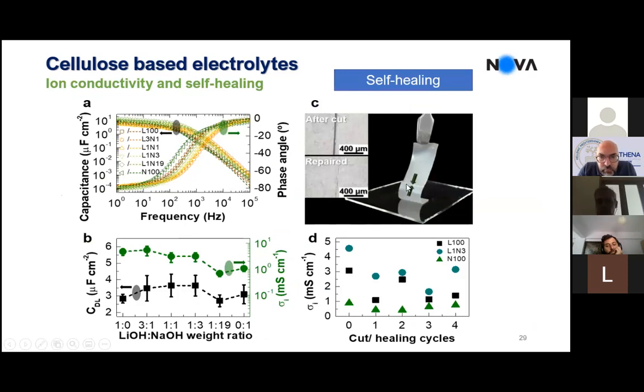The good thing about this is they have CMC, and if you remember, CMC is hygroscopic. So if you damage these membranes, if you cut them, for instance, you can repair them by exposing them to high levels of moisture. And here is the bad thing that I have to say about this type of approach.